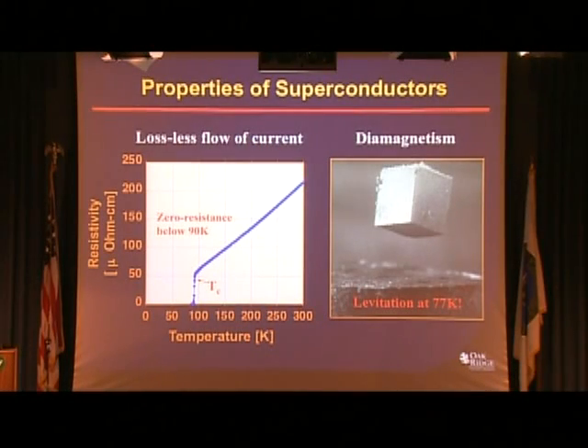Two key properties of superconductors: as you cool them down below a transition temperature called TC, the material goes superconducting, in other words, without resistance. And if you were to take, for example, the YBCO-based superconductor, a puck of it, cool it in liquid nitrogen well below the transition temperature, and you put a permanent magnet, a property of the superconductor is that it likes to behave like a diamagnet, expelling the magnetic flux lines, and hence the magnet levitates.